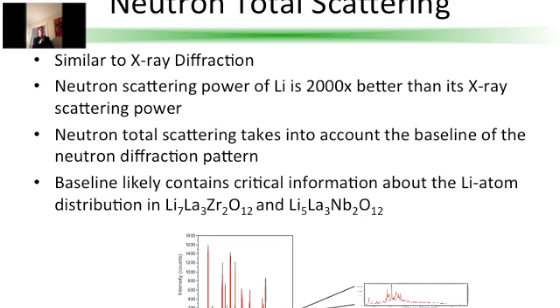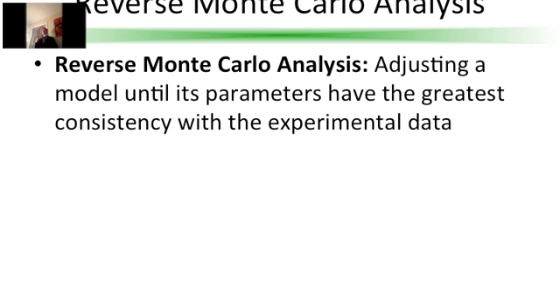Even more importantly, unlike in X-ray diffraction, where we only examine the peaks in the diffraction pattern, I will be using neutron total scattering, which takes into account the baseline as well, which often contains important details about the crystal structure. To analyze the neutron total scattering data, I will be using a technique called reverse Monte Carlo analysis, whereby adjusting the model until its parameters have the greatest consistency with the experimental data, I will be able to determine the exact distribution of lithium atoms in the samples.